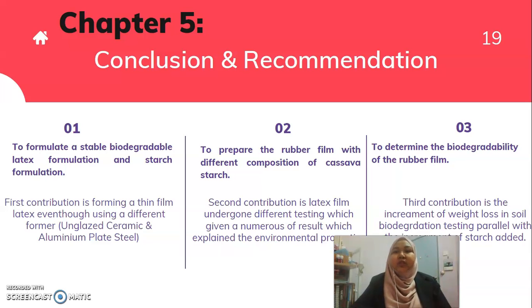As you can see, there are 3 objectives that I mentioned before. The first one is to formulate a stable biodegradable latex and starch formulation. The first contribution is forming a thin film latex, even though using different formers, unglazed ceramic and aluminum plate steel. The second one is to prepare the rubber film with different compositions of cassava starch. This second contribution is that the latex film underwent different testing, which gave numerous results explaining environmental properties. The third one is to determine the biodegradability of the rubber film. The third contribution is the increment of weight loss in soil biodegradation, at 30 phr. Okay, this 30 phr showed weight loss in soil biodegradation testing in parallel with the increment of starch added.